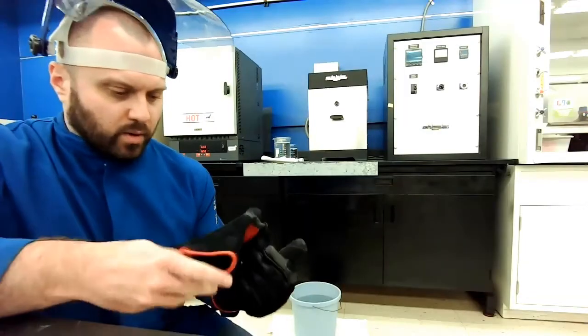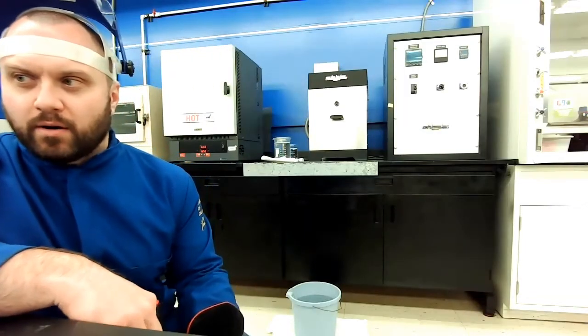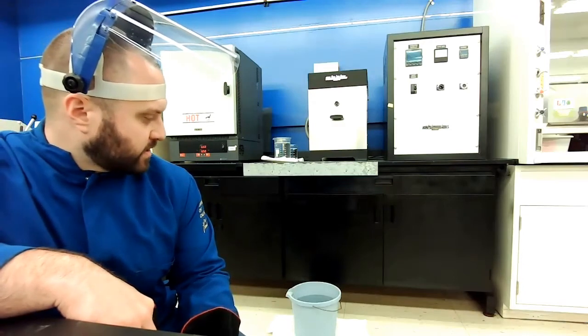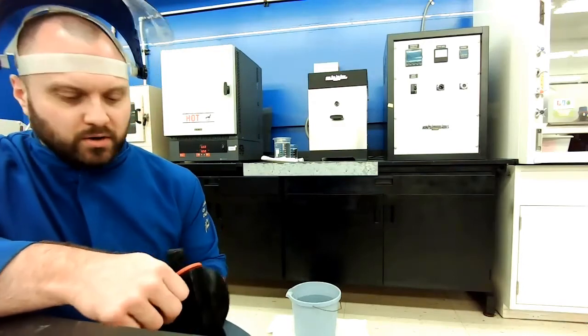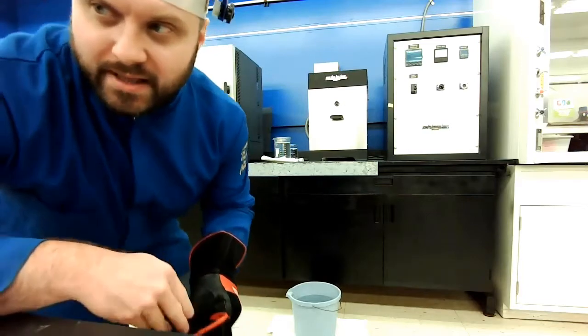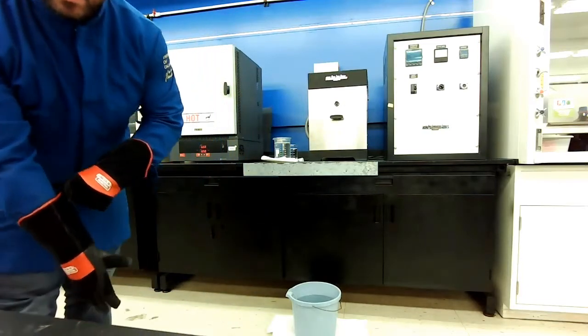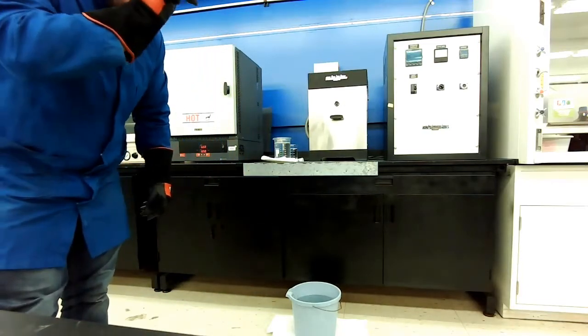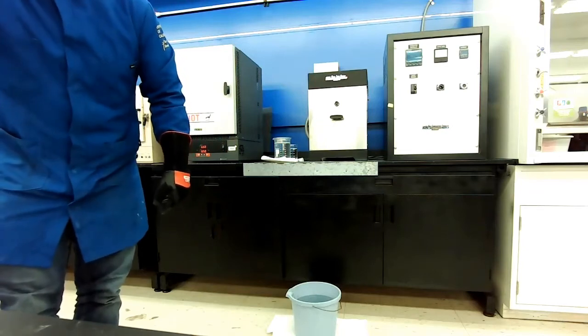All right, so we're back. It's been our 3 hours at our 650 degrees C, so we should have formed our coarse pearlite. We're gonna go in and take this sample out, rapidly quench it in this salt water, and then rinse it off.